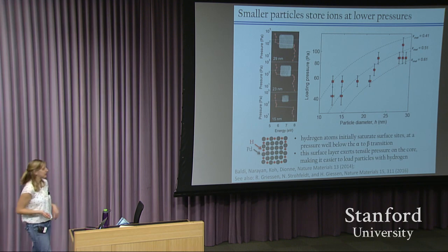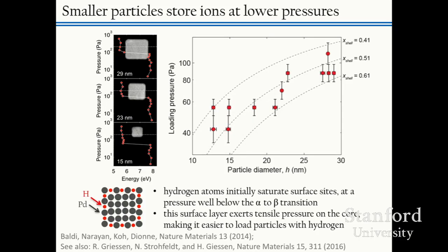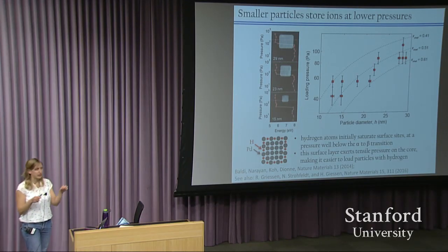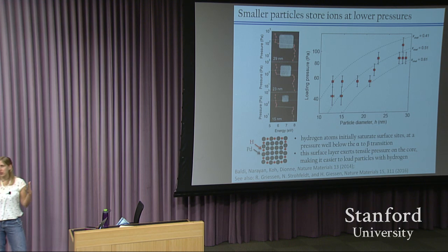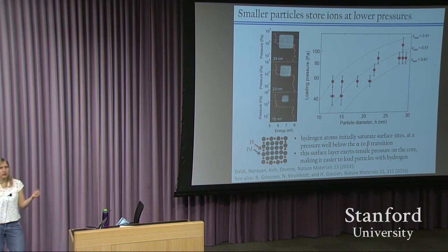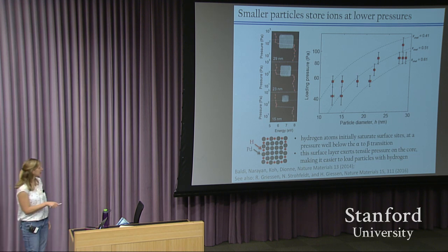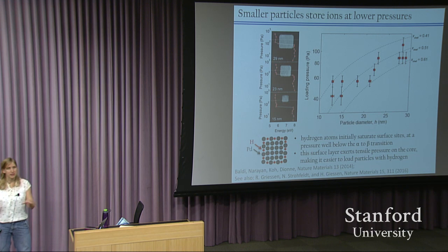One way of rationalizing what's happening there is that when hydrogen gas catalytically splits into hydrogen atoms at the surface, hydrogen can sit at those interstitial sites, saturating the surface sites. And I told you that when we transition to the beta phase, there's a pretty big change in volume, a 10% change in volume. So right at the surface, these fully saturated sites are lattice expanded, and they're starting to pull on the core of the nanoparticle where hydrogen has not yet entered. So there's essentially tensile strain at the surface that's acting to pull apart the nanoparticle, making it easier for hydrogen to get in there if the particle is smaller, because those surface layers have more of an effect on those smaller nanoparticles.